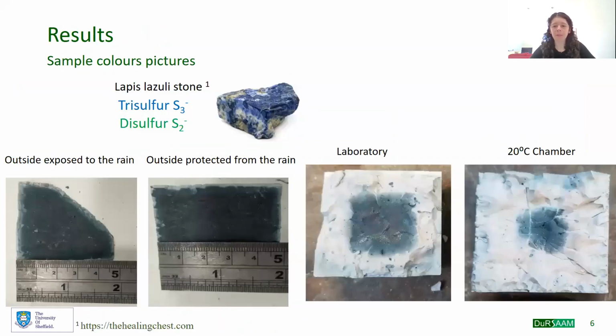After 3 months of carbonation, the samples looked like this once opened. You can see that there are different colors. This is due to the oxidation of the sulfur. It's a mechanism well known because of this stone, the lapis lazuli stone. And you can see, for example, in the laboratory picture that there are